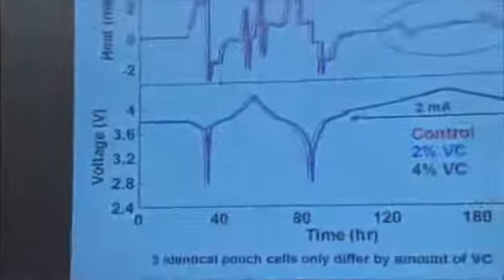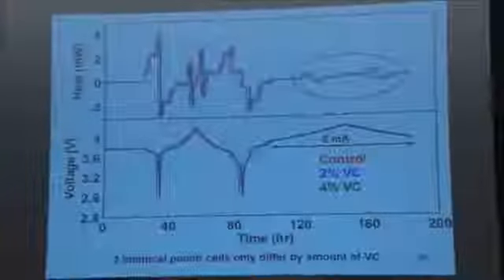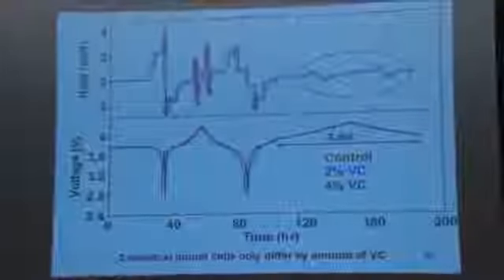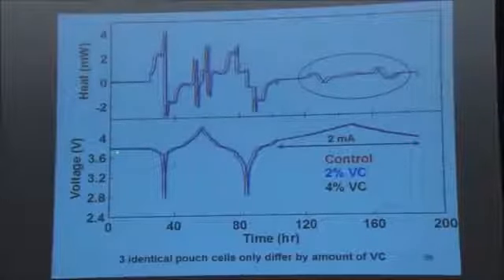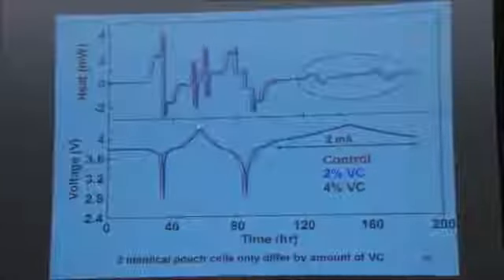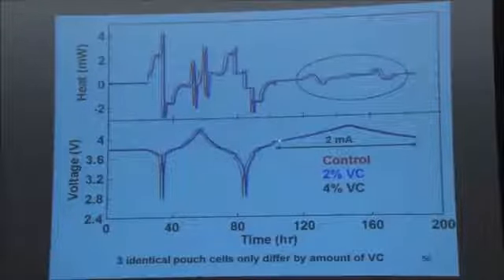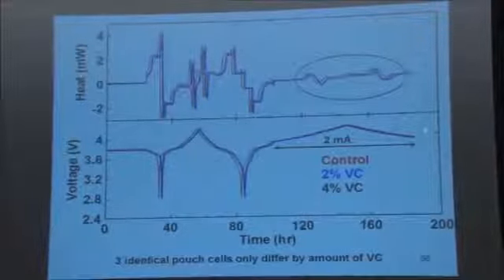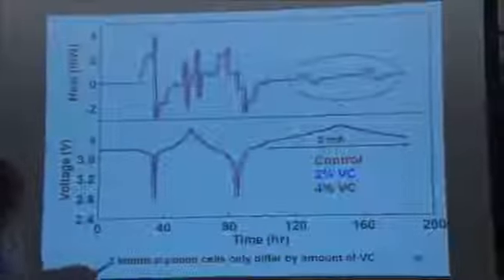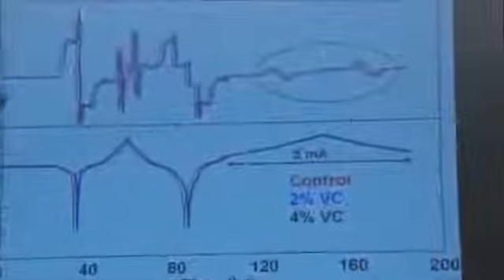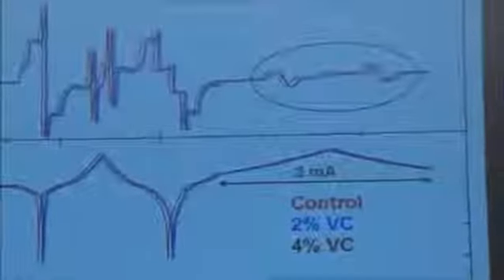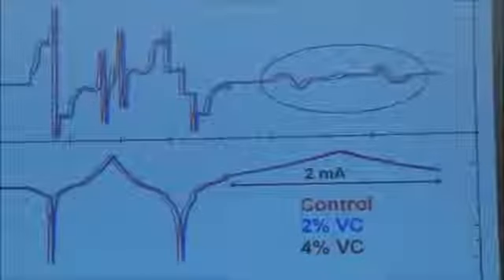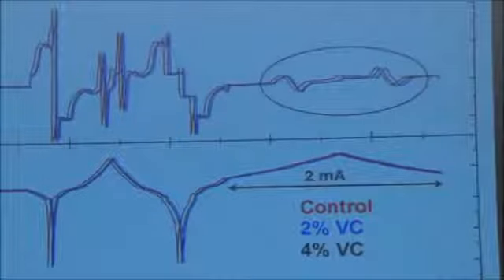Okay, so here are some experiments. These are identical pouch cells, lithium cobalt oxide graphite pouch cells. One has control electrolyte and the others have different amounts of vinylene carbonate in them. They did the first charge and discharge, then they went open circuit, and then we discharged them, charged them, discharged them, charged them. And then we did a very slow charge and discharge, and I want to just concentrate on this range. If you look very carefully up here, you'll notice on the heat scale, there's all kinds of stuff happening. Entropy changes, polarization, and so on, but the cells are identical.